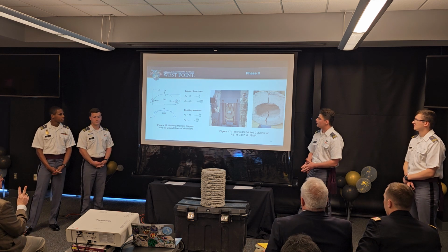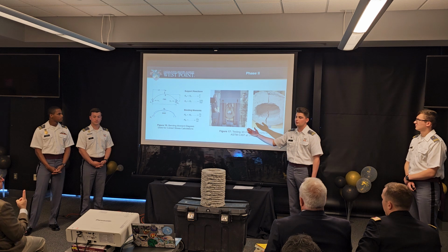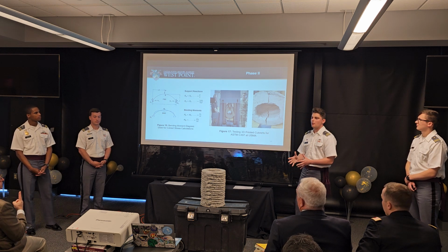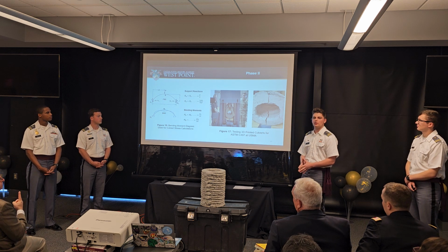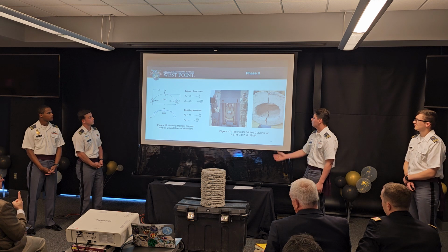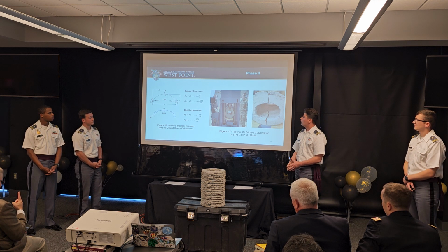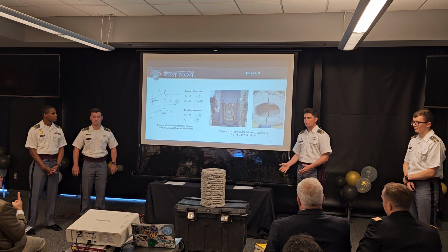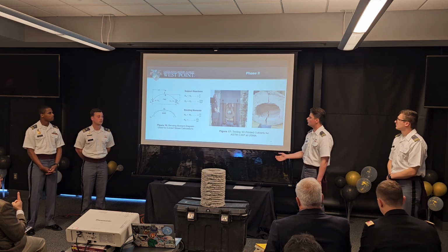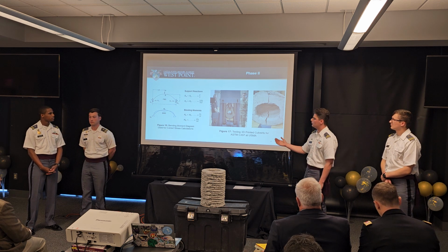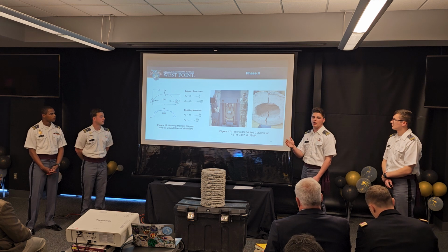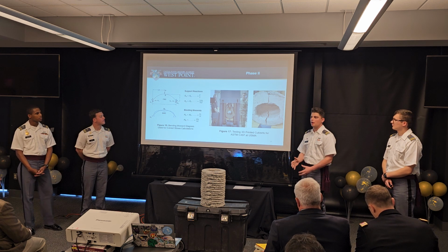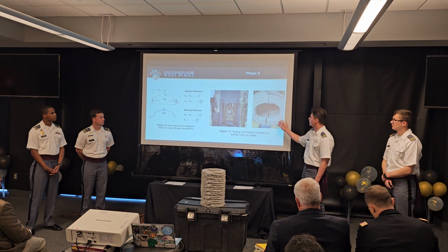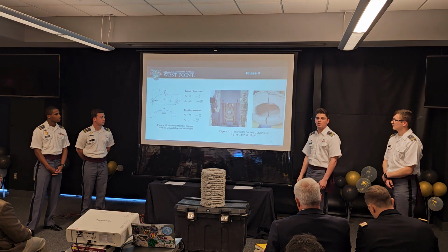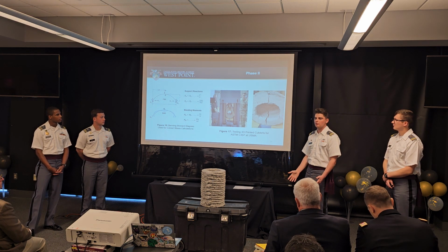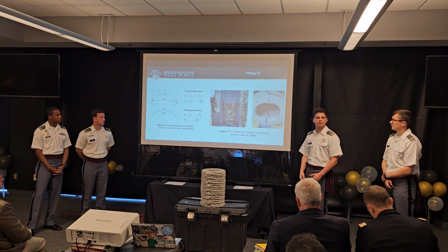So we assumed that this would be a fixed arch, as shown in figure 16. When we were testing these, we underwent ASTM C497, which is shown in figure 17. We were able to conclude that our assumption was supported. Based off the moment diagram in figure 16, the maximum moment would occur at the top and bottom of the arch. As you can see, based off of this image here, the failure occurred at the crown and the base of the culvert, which means that our assumption, although not proven, was supported.